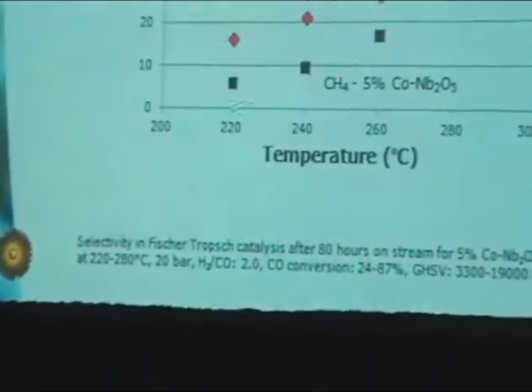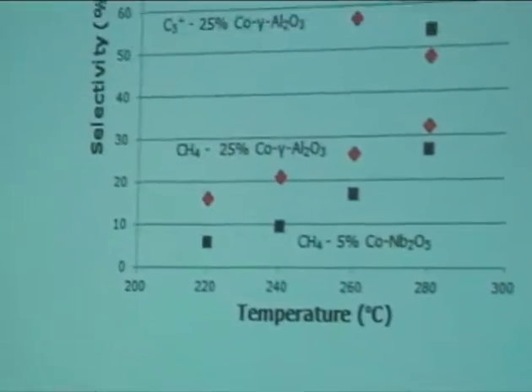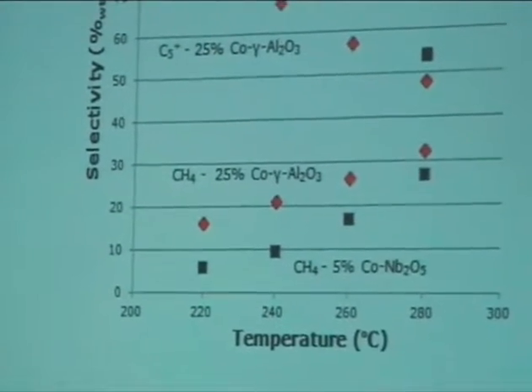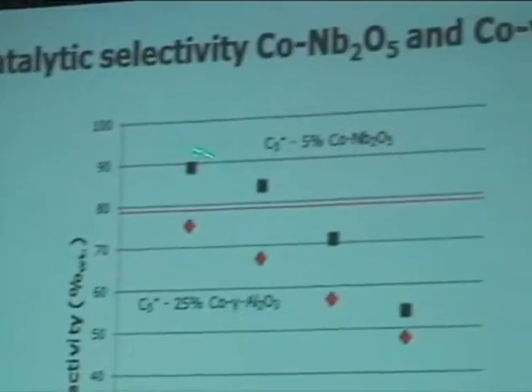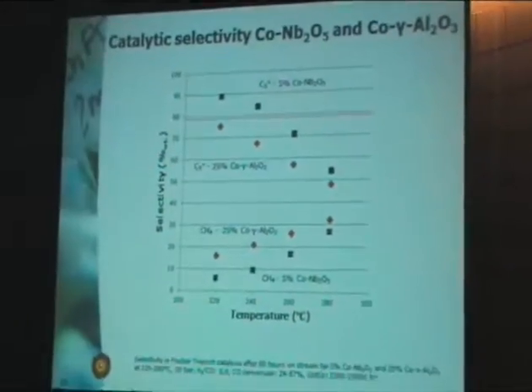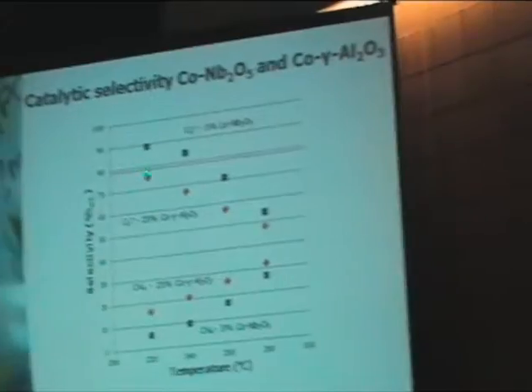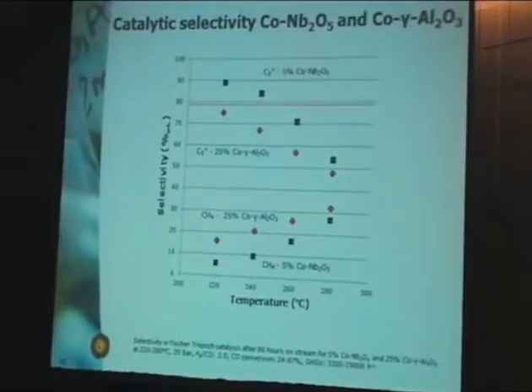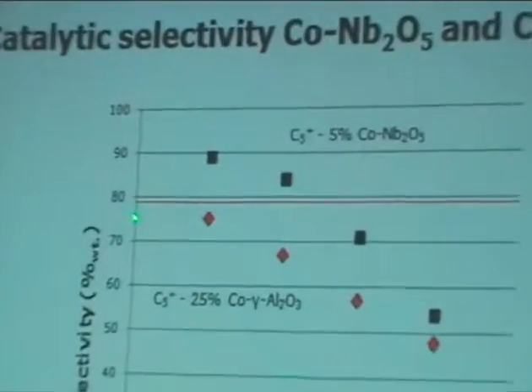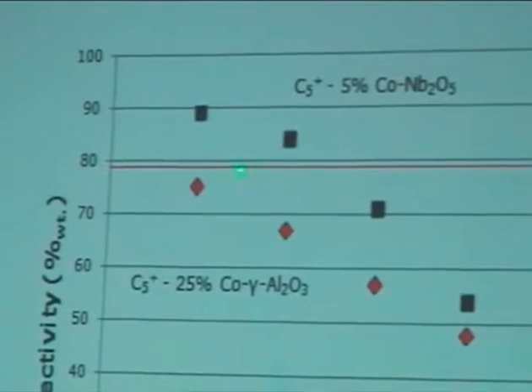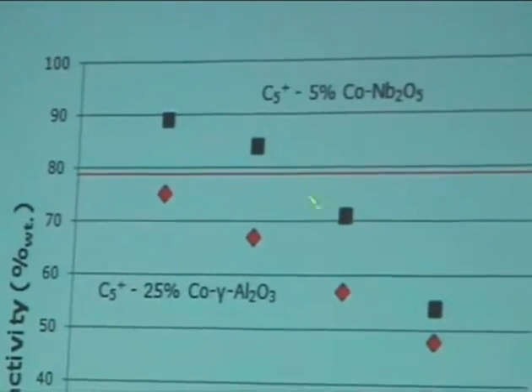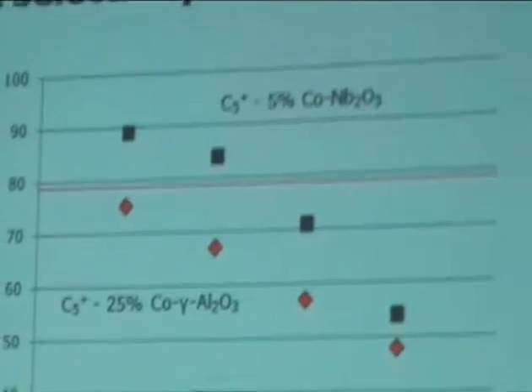Again, it's not only activity, it is selectivity. So if we plot here the selectivity, there's methane on the one hand and C5 plus on the other. And consistently, the C5 plus selectivity of cobalt on niobium is much higher than the C5 plus selectivity on gamma alumina. And our proposal is to harvest that high selectivity in the sense that if you put a certain target, let's say around 80% or so, you can run the cobalt niobium catalyst at much higher temperatures than you can operate the cobalt on gamma alumina.